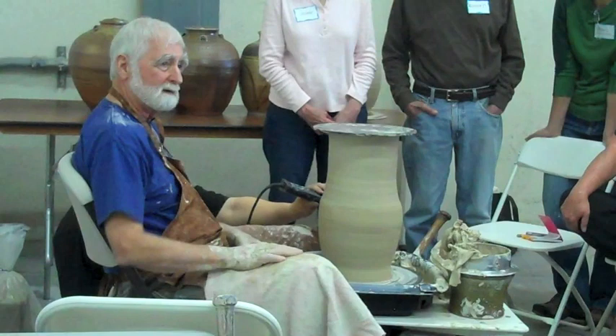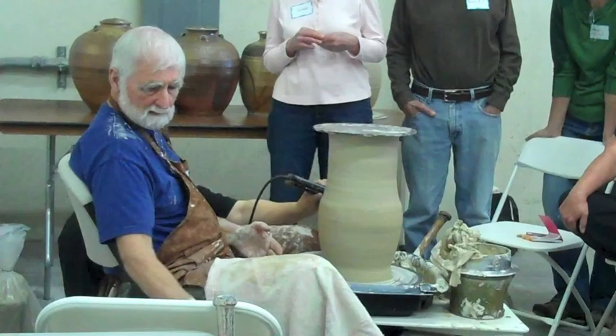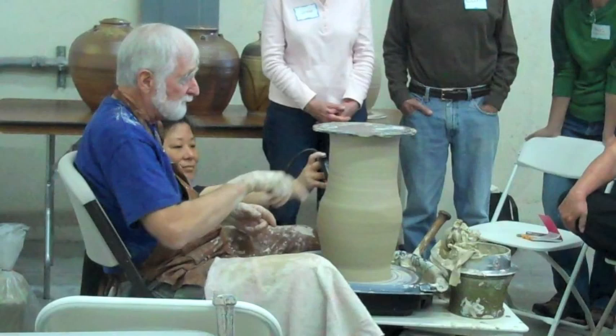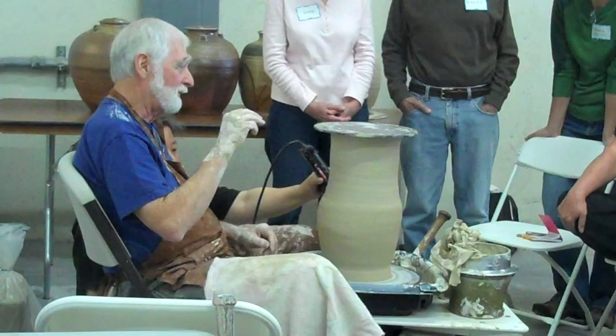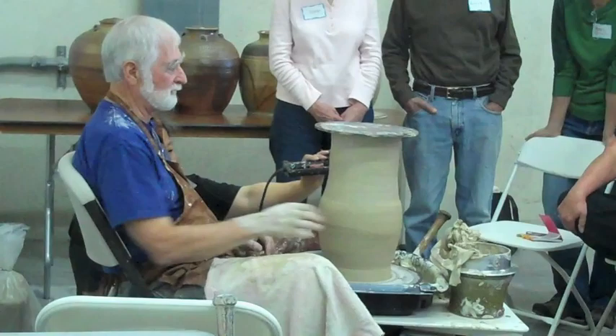Then I turn it over, and usually the glaze is a little heavier on the bottom. So what I do is I have a couple of bamboo holes that are triangles that it sits on, so there's minimal contact. Right after I pour the glaze, I take my finger and run it right up against the clay rim all the way around. Then there's only three spots I have to deal with when I turn it back over, where the rot and the holes were. Generally, I just take a little green scrubby that's been used a lot. It's soft. And just shave those lumps down. Then take a paintbrush and fill in there so that it looks pretty smooth. There's going to be a little difference in those three spots, but it's not enough usually to matter.